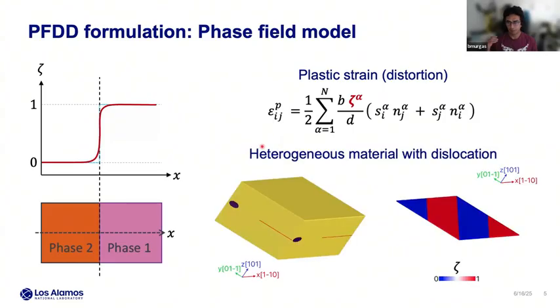And what we're doing is that we use fast Fourier transforms as spectral solvers, and for that our domains need to be periodic. So this is an example of what a simulation setup looks like for a heterogeneous material. You have in yellow one phase, in blue another phase, and here in red you have the dislocation variable, the phase field variable. And when you see just the dislocation variable, you will see this kind of pattern here. So as I said, it's periodic. You have periodic boundary conditions, and here our dislocations will be between the red and blue colors, because this is the transition between 0 and 1.